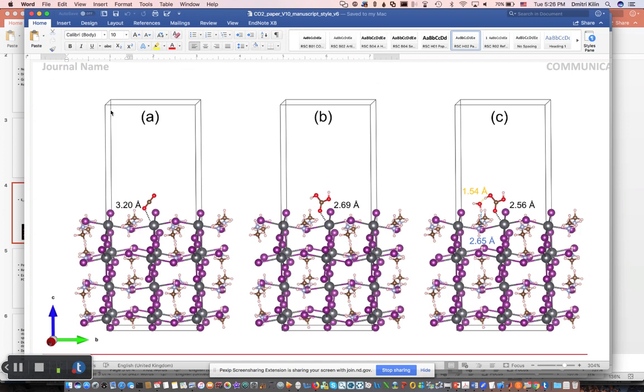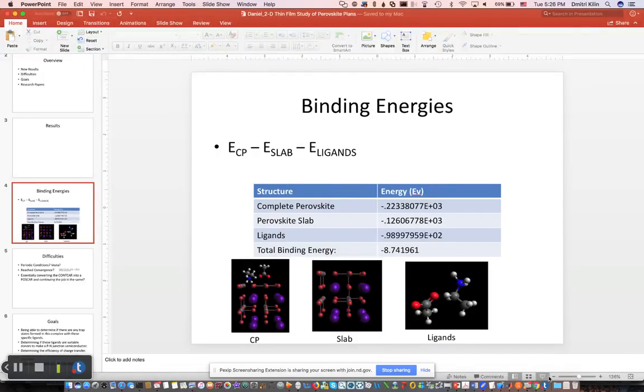So technically, the bigger your vacuum layer, the better, if you can do 30, 50 angstrom. You don't want to have 0 for the vacuum layer. You want to have it as big as possible. It's just technically too expensive to have it as big as possible. And if you take more than 10 angstrom of vacuum, everything will converge and stop changing. But there will be nothing wrong with putting 100, other than the job will run for a year or whatever, 2 months. Let's go back to the presentation by Daniel.